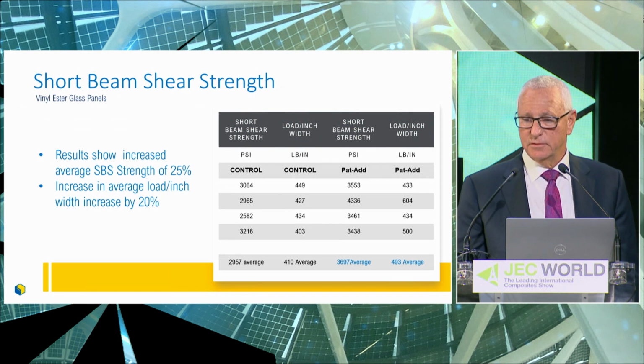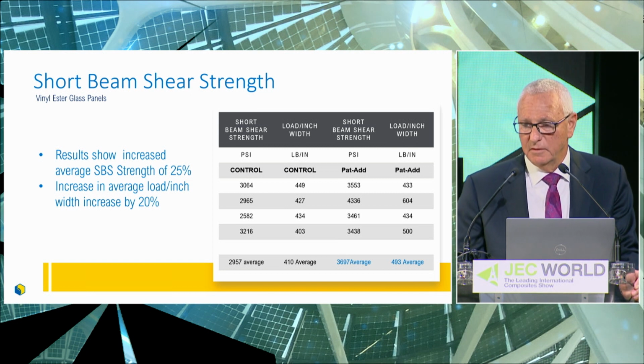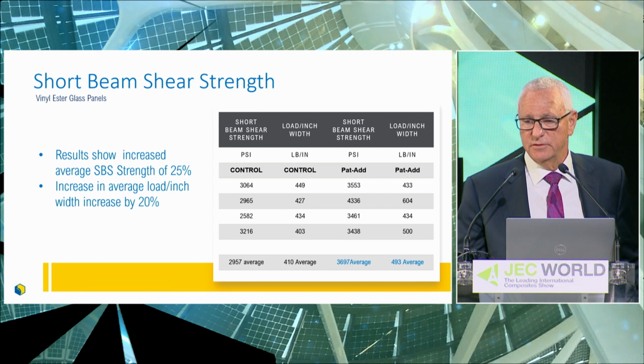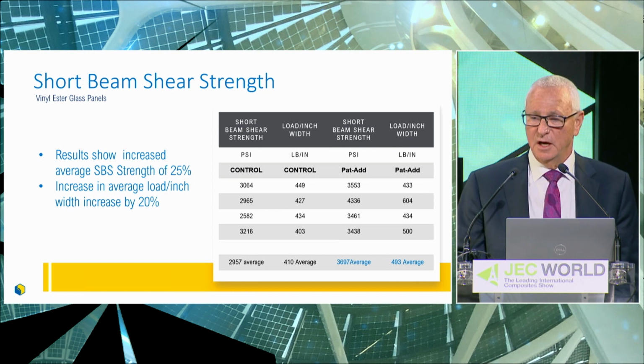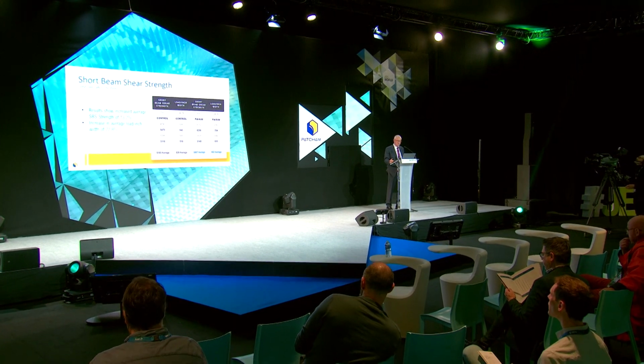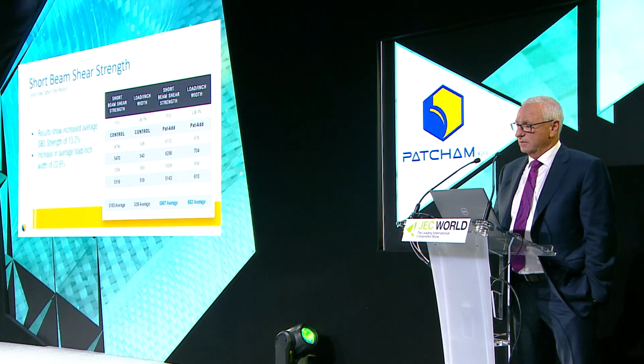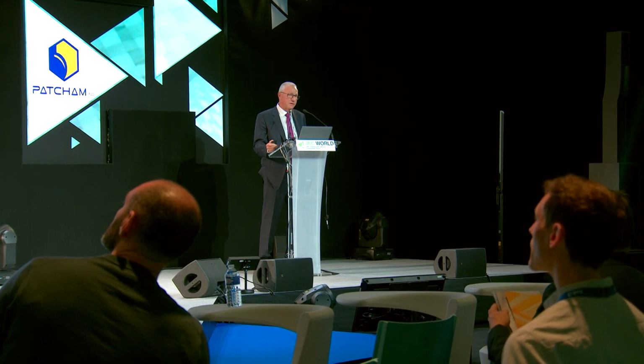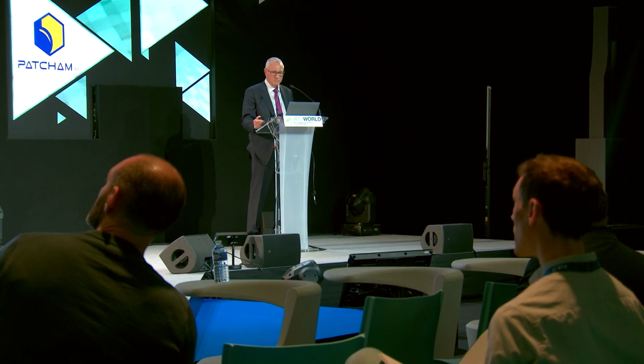And here's the results. So you look at the table, and this is the vinyl ester glass panels. In the vinyl ester glass panels, we showed an increase in the short beam shear strength of upwards of 25%. That's a pretty significant number. The vinyl ester carbon fiber, we showed a 13% increase in strength through just wetting the substrate better and wetting the reinforcing fibers better. And on the epoxy carbon fiber, we showed a short beam shear strength increase of 17%. By the way, I didn't run the Instron. Had these done in an independent lab, so nobody skewed the results.